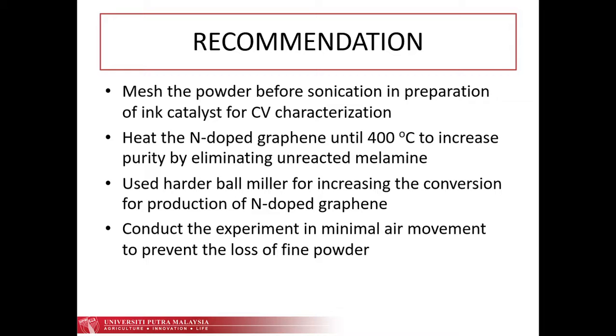Then, because the unreacted melamine overshadowed the graph of the N-doped graphene in the XRD analysis, it is recommended to heat the N-doped graphene until 400 degrees Celsius so we can eliminate all of the unreacted melamine. Then the third recommendation is to use a harder ball miller for increasing the conversion in the production of N-doped graphene. In the research paper, they use a stainless steel ball miller, which will give better production of N-doped graphene compared to this zirconium oxide ball miller, because stainless steel is harder.